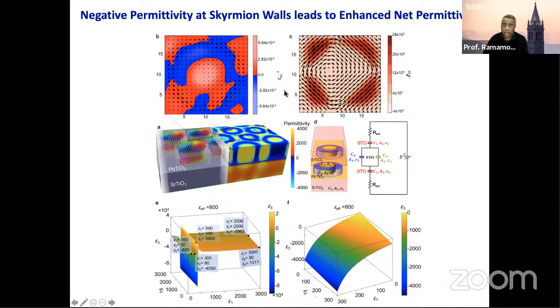Now I can go in and calculate the permittivity, which is related to the susceptibility. And actually you plot the 1 by the permittivity, because otherwise you get into goofy mathematical singularities. But if you look at the inverse of the permittivity, which is what we're looking for, right around the periphery of the skyrmion, which is right around here, you see that the permittivity is negative. And therefore, if I plot the entire structure in a macroscopic sense, I have these cylindrical skyrmions where the periphery of the skyrmion is a region of negative permittivity.